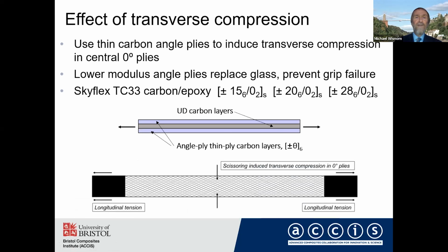And the same thing happens in transverse compression. So we used another variation on a similar sort of approach, using thin carbon angle plies to induce transverse compression in UD plies in the middle. So here we've got UD plies in the middle, we've got angle plies on the outside, and because of the scissoring action of those angle plies, they put transverse compression across the width of the specimen. We can induce quite high levels of transverse compression by varying the angle on those specimens.